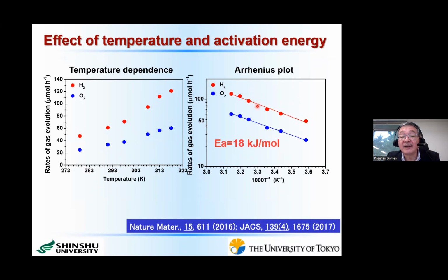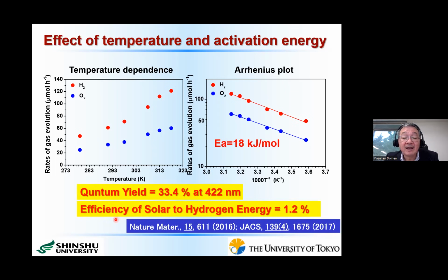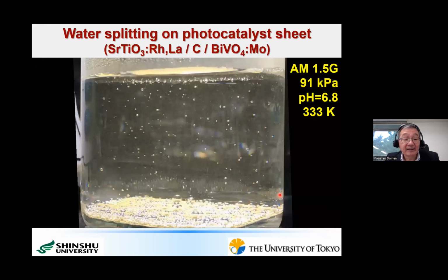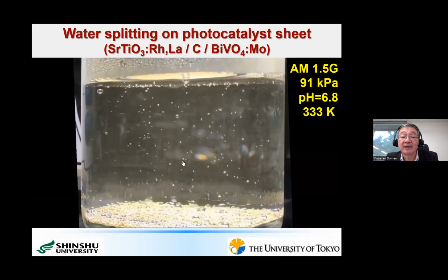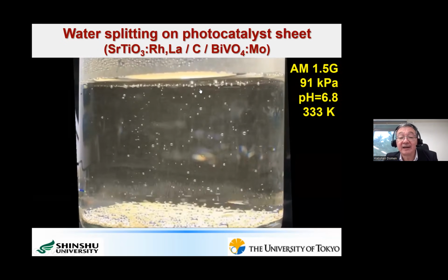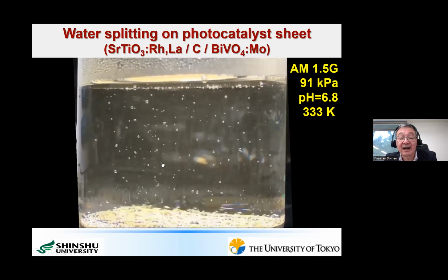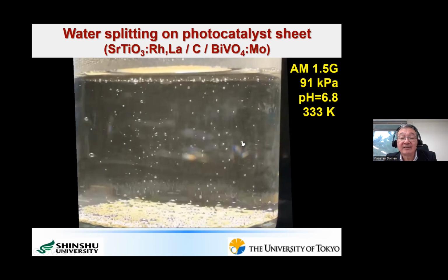From this Arrhenius plot, we can get the activation energy of this water splitting reaction, which is 18 kilojoules per mole. At the highest temperature, we could get an apparent quantum yield of about 33% at about 420 nanometers. This is much better activity than the suspended system. In this case, the solar-to-hydrogen energy conversion efficiency was about 1.2%. This is still much lower compared to photovoltaics, but I will come back to this number later. And this is one of the typical experiments using this kind of photocatalyst sheet. In this case, we use carbon as a contact layer, and it evolves hydrogen and oxygen exactly in a 2:1 ratio in just distilled water, as shown here.